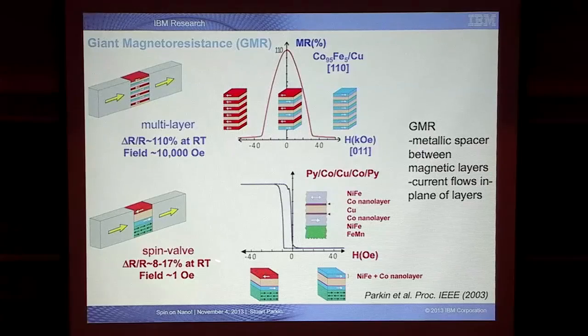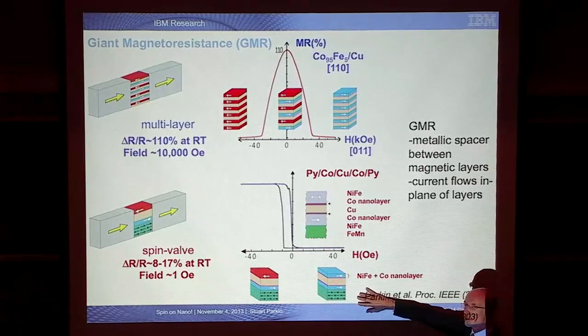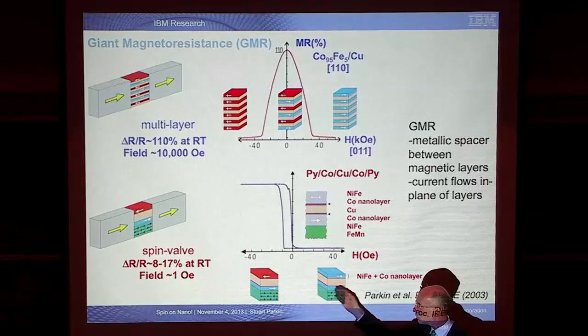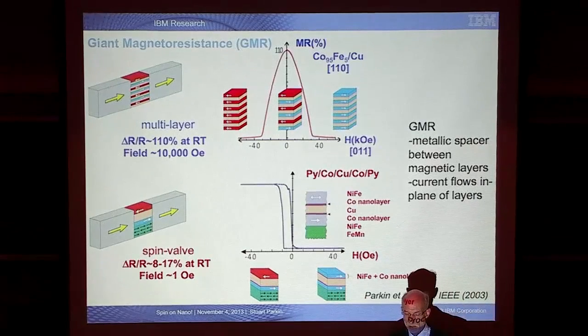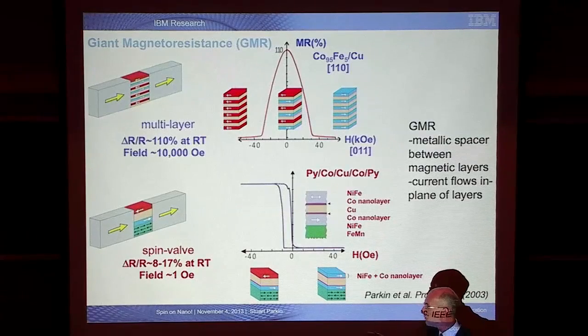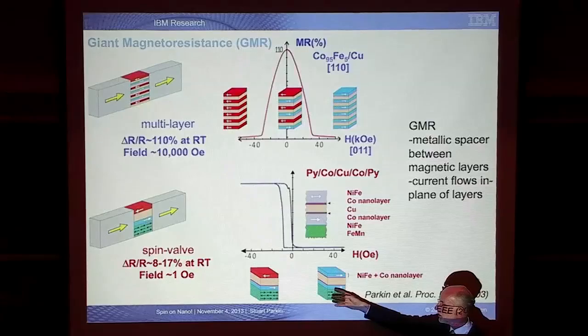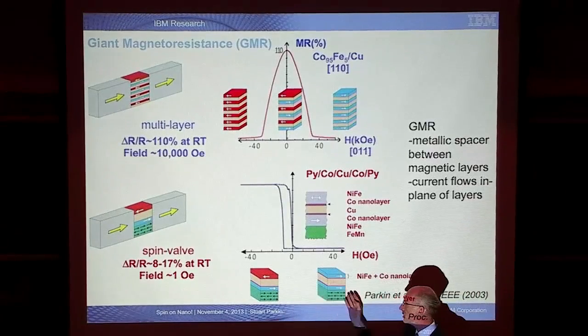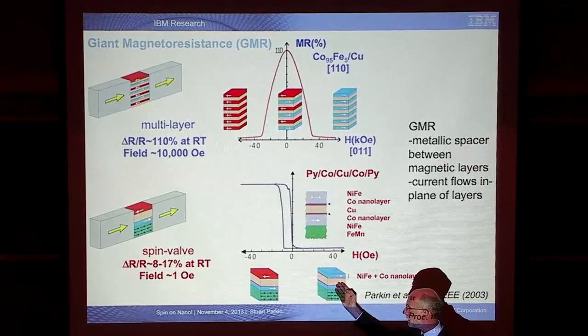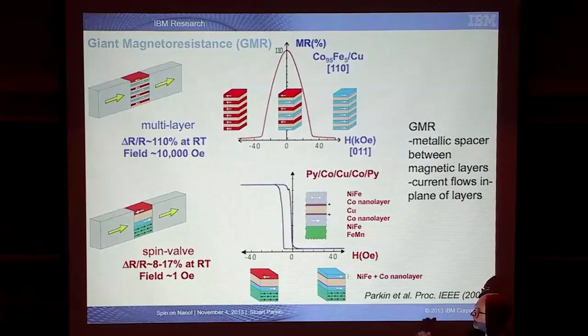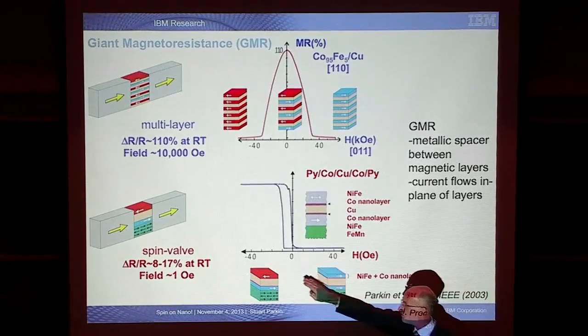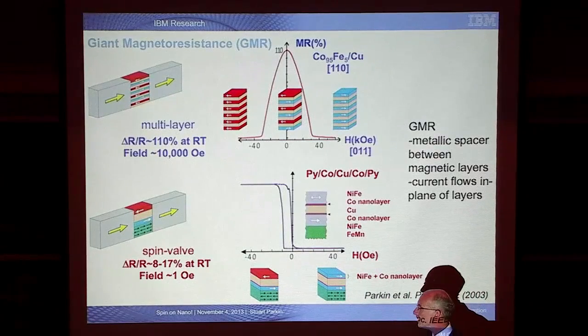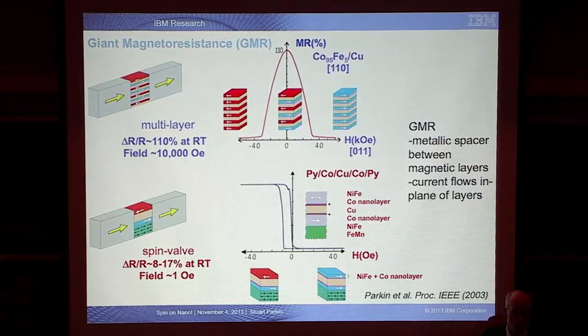And we then developed this thing we called the spin valve, whereby essentially by spin engineering, we could create structures in which the magnetic moment of one layer is essentially fixed for all fields that we might apply, by using a trick: coupling a magnetic film to another type of magnetic material called an antiferromagnet. There's no net magnetization, but at the interface there's an internal magnetic field that this layer sees. So essentially that moment is fixed by this spin engineering concept. We then have a layer of copper which is a lot thicker than in these multilayers, so there's no net magnetic interaction between these layers. And then we have a second magnetic layer on the other side of the sandwich, which will then change its moment in response to magnetic fields as small as the Earth's magnetic field or smaller. So we're extremely sensitive to detect tiny magnetic fields in this sandwich structure.